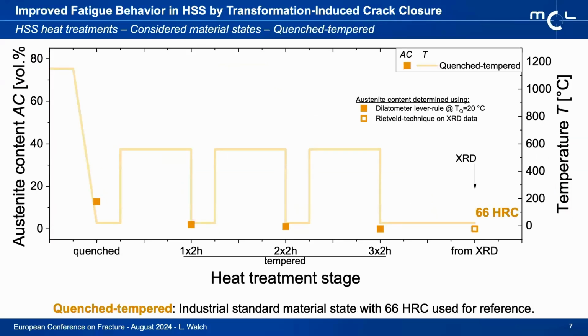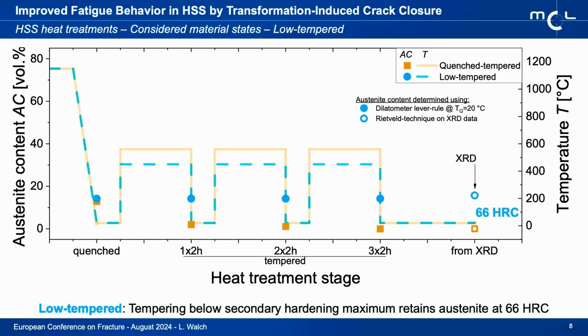We started out with a conventional commercial standard state as it's used in the industry, which has no retained austenite and an impressive Rockwell C hardness number of 66 HRC, so about as hard as it gets. Then our first material state with retained austenite was simply achieved by lowering the tempering temperature below the secondary hardening heat treatment, just so that the secondary hardening precipitation, which usually occurs and destabilizes the retained austenite so that it transforms during the full heat treatment, did not occur. And we had about 15 volume percent of retained austenite left after the full heat treatment.